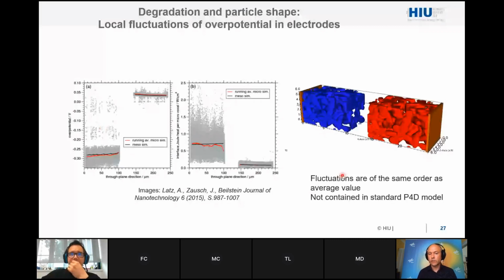So if you do cell simulation, I mean, this is very often done to see at which point you get plating. Then you would do a P4D simulation, the homogenized model, and you find, well, yes, you are safe. But then you do the microstructural simulation, you see, well, maybe there are potential fluctuations at that point which are really going to maybe too low, and therefore causing a plating event, which is not covered by the P4D model.